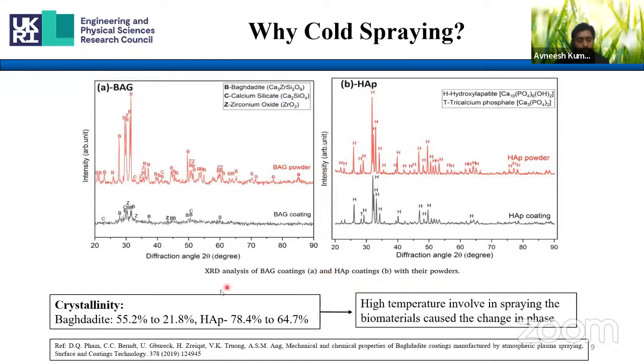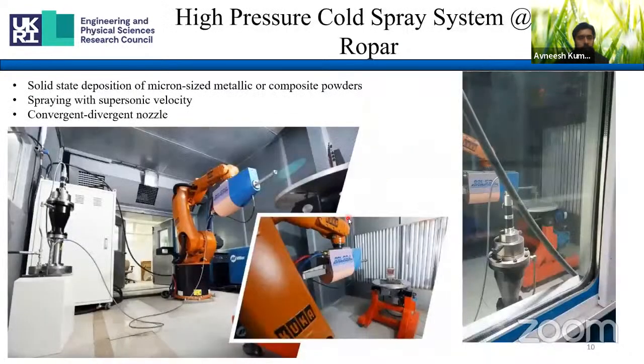So this phase change problem can be avoided using cold spray, because cold spray is basically a solid state deposition technology where micron size powder particles are propelled with supersonic velocity and strike the substrate to form bonding, mechanical bonding or metallurgical bonding. To attain that supersonic velocity, a convergent divergent type of nozzle can be used. This is the cold spray setup we have at IIT Ropar, and this setup can spray up to 50 bar of gas pressure and 1000 degrees of gas temperature.